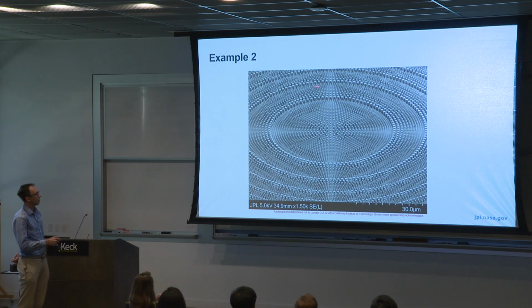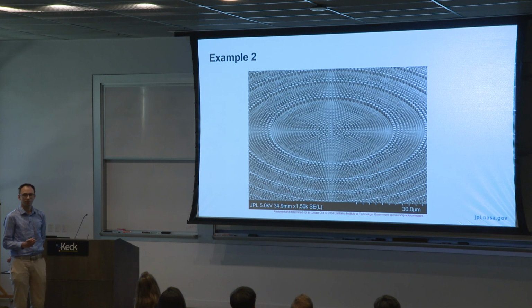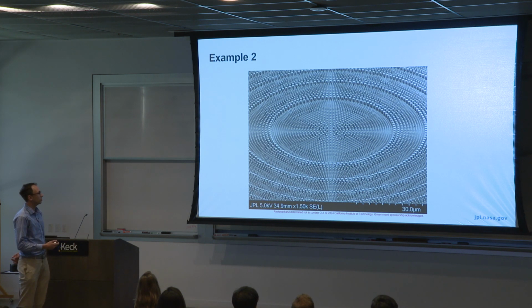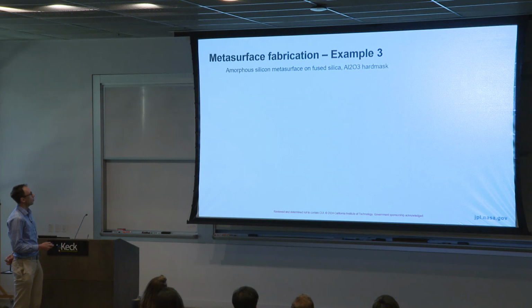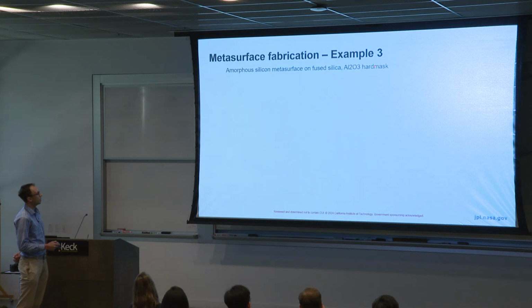You can clearly tell from this image, this is a very different type of aspect ratio feature than we saw in example 1. And this, at the heart of it, is because this material doesn't etch nearly as well as silicon. Okay, example 3. Now I'm going to use a different type of hard mask, aluminum oxide, which is fairly popular these days because it's a very durable material that's fairly easy to deposit.